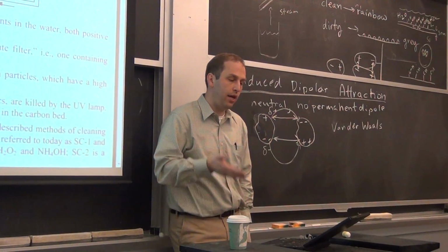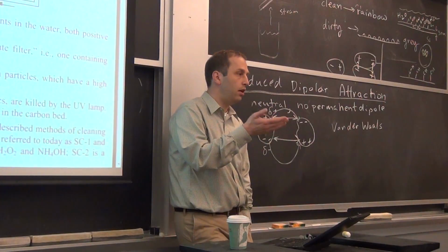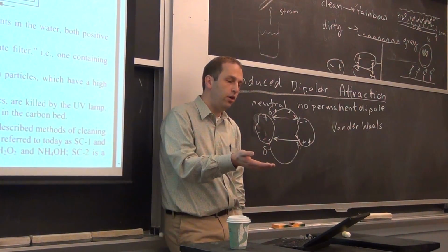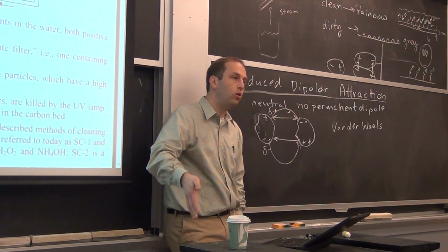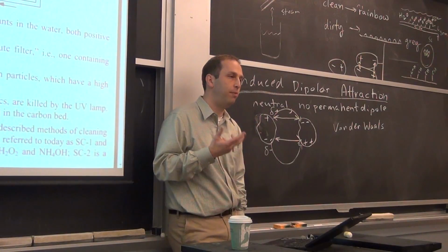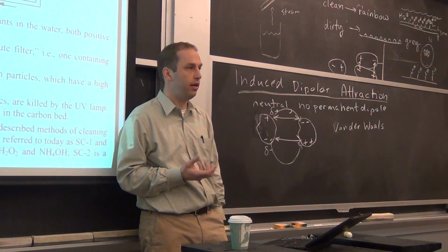So say you're doing a liftoff in a hot liftoff solution, and then you go into this cold deionized water, that hot metal that you just deposited will be etched really strongly and corroded by the deionized water.